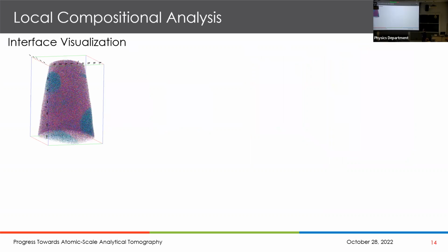And if we take this one step further, you can say, well, because you know where all the atoms are, you can calculate the local composition about any point in space. And so you can actually draw iso concentration surfaces. So for example, now I'll turn off these atoms and you can see the iso concentration surfaces. Those surfaces surround a region, say, of high aluminum content, and outside it's a lower aluminum content, if you're picking an aluminum iso surface.